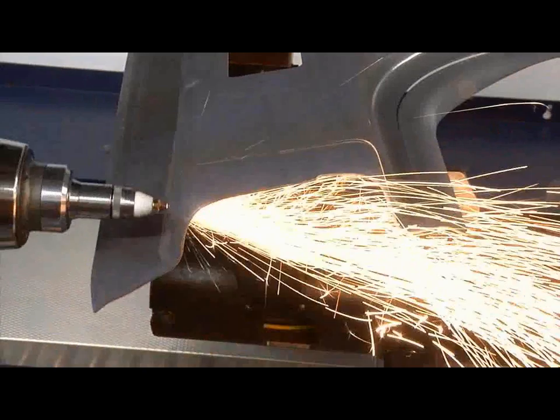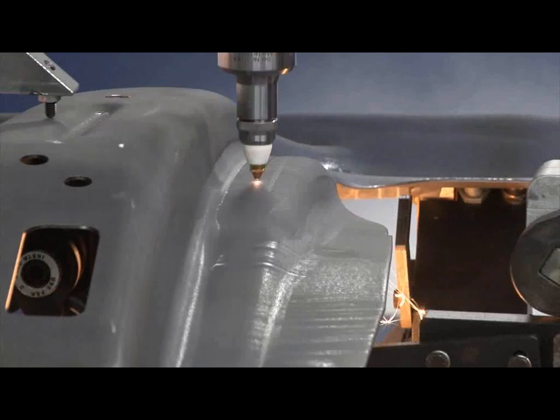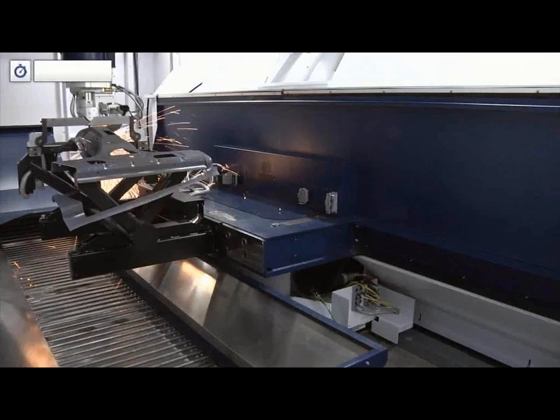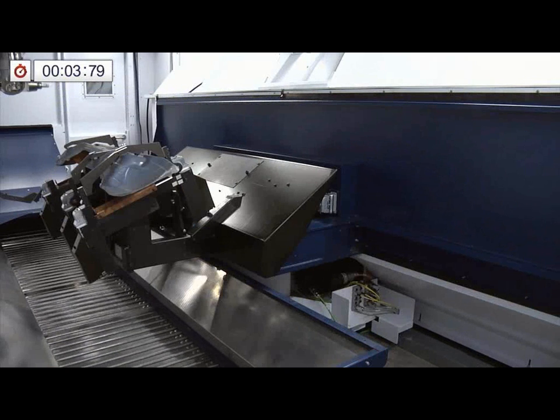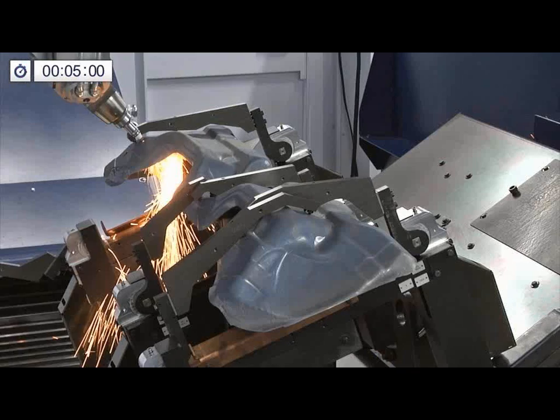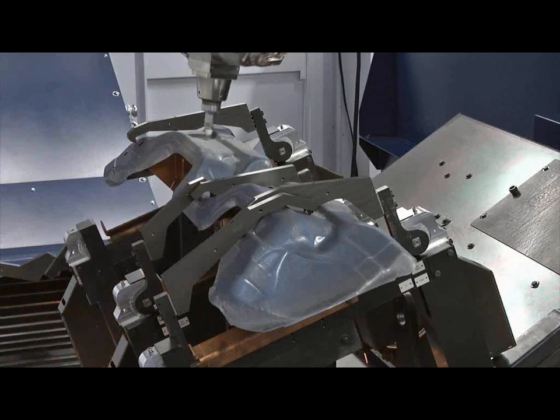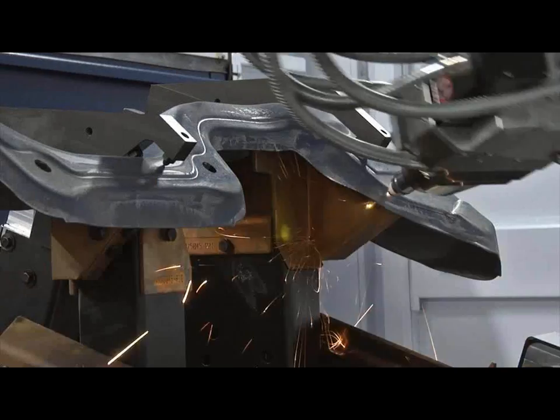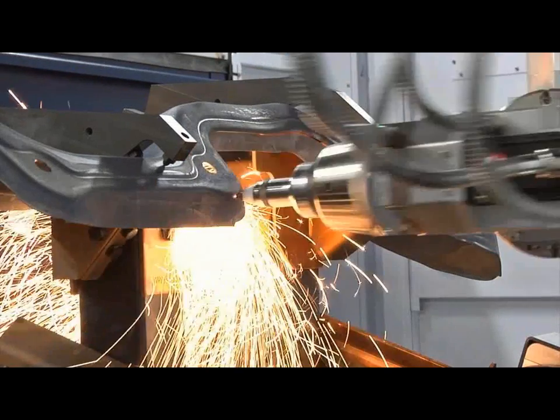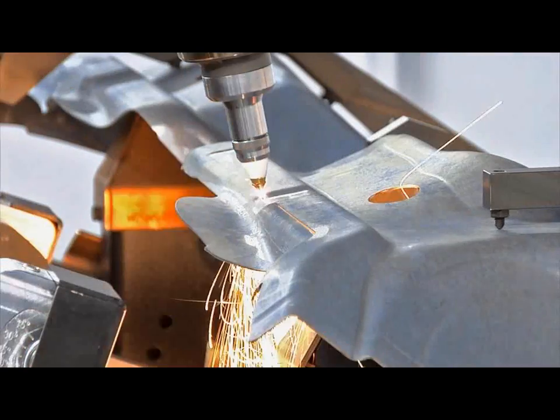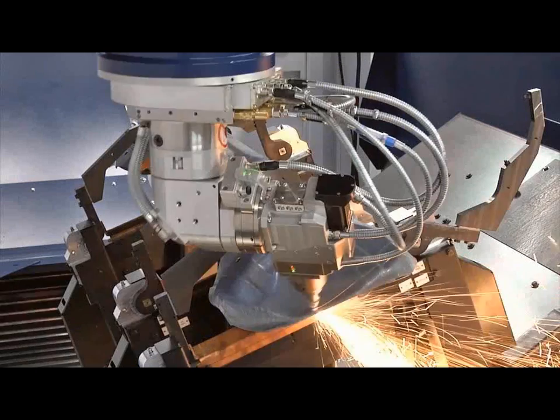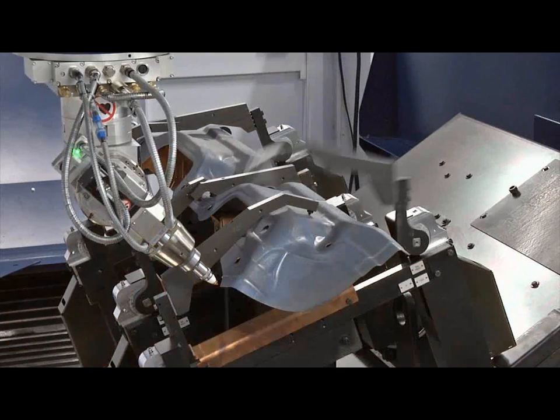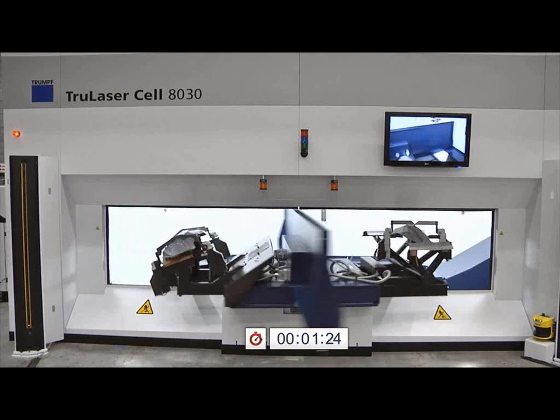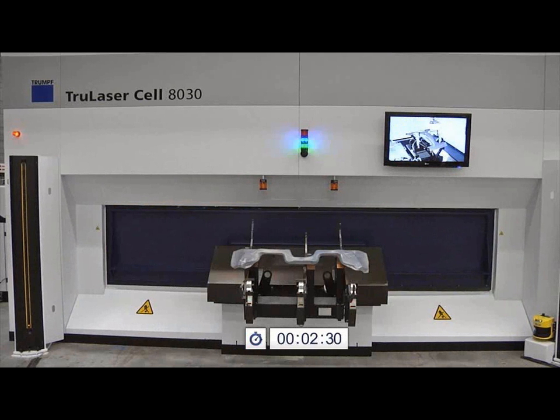And of course, what you can hopefully see well in your screen presentation, is the very high agility of the machine and also the changeover time from part to part that is shown here. So from turning the laser off and putting the head away to a safe position, putting a new part into the workstation, approaching the part again, igniting the beam. That's pretty much the time from part to part. It takes right about 5 seconds here. If we only look at the rotation time, it's a little bit over 2 seconds, roughly 2.5 seconds.